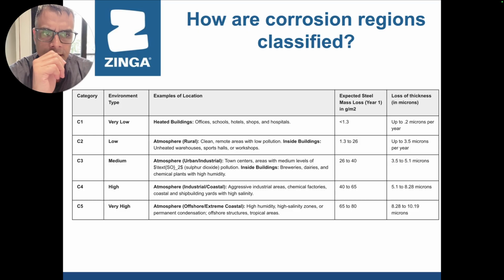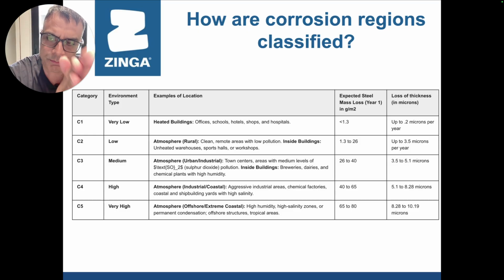Now, in this case, what is important to know is that there is an expected steel mass loss and there is a loss in thickness of the steel. Both are very important points to know. Let's talk about C1. An example is a heated building, an inside building. The environmental corrosion rate is very low, offices, schools, hotels, etc., where the grams per meter square is less than 1.3, and even there is loss in material which is up to 0.2 microns per year.